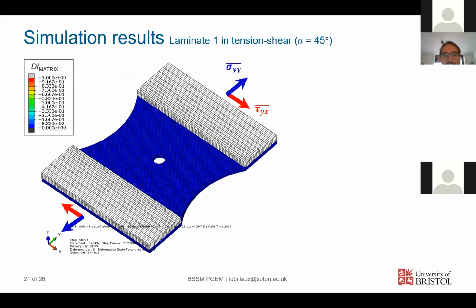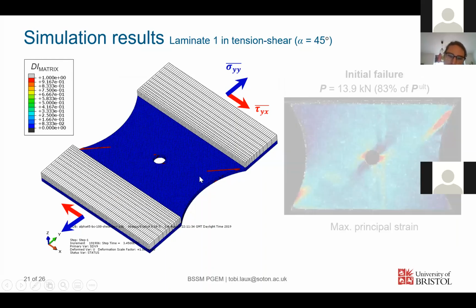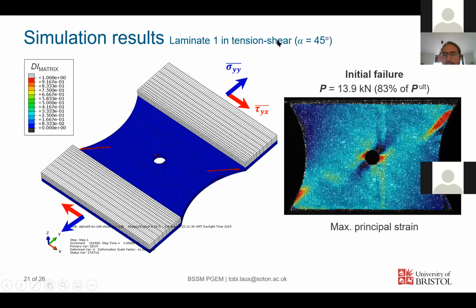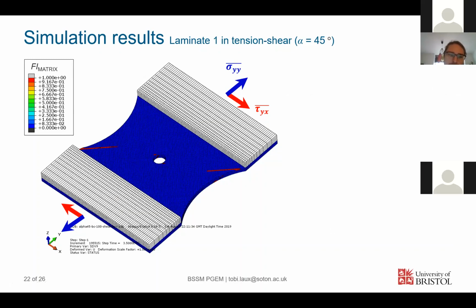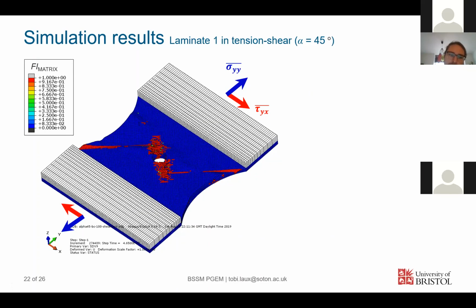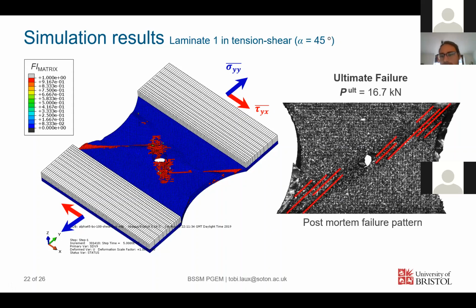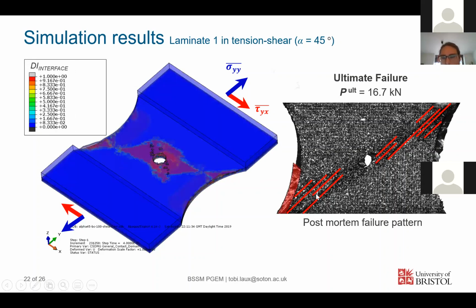Now, if we look at simulation results, so this is actually a video. So you have an initial failure event. And I should say this is a laminate 1 specimen in tension shear, just for an example. If we then look at our DIC, we actually can see like, oh, these initial cracks in red, matrix failure, we can see that in the strain map really, really well. So that looks good. And if we then carry on to ultimate failure, we can also see that the overall crack patterns here actually match. And even more, if we look at delamination, we can even see that the delamination planes here, which we can see at the specimen, seem to match the predictions quite well.